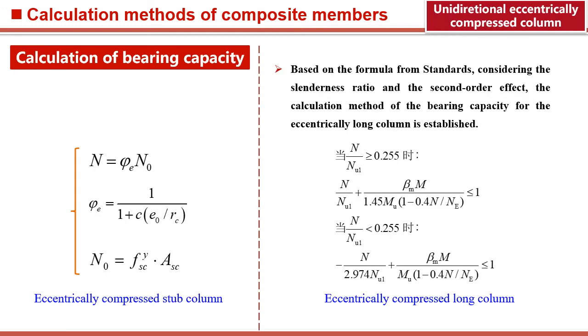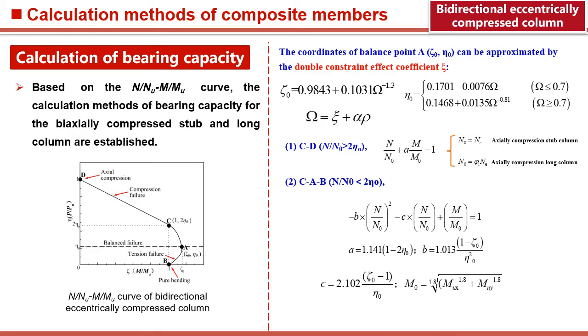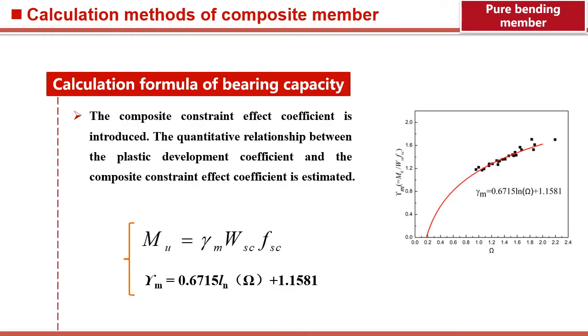For the calculation method of unidirectional eccentrically compressed long columns, the influence of the slenderness ratio and the second-order effect is considered. Considering the double restraint effect for the bidirectional eccentrically compressed column, the coordinates of the balance point are determined, and the design method is established. Regarding the pure bending member, the composite constraint effect coefficient is introduced, and the quantitative relationship between the plastic development coefficient and the composite constraint effect coefficient is estimated.